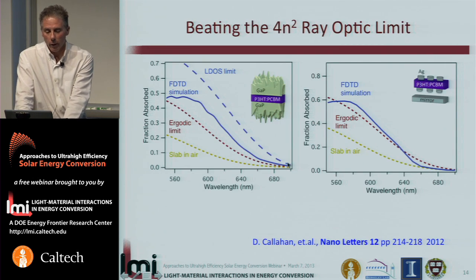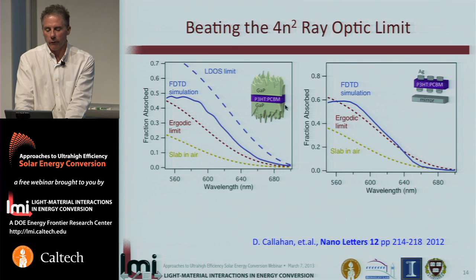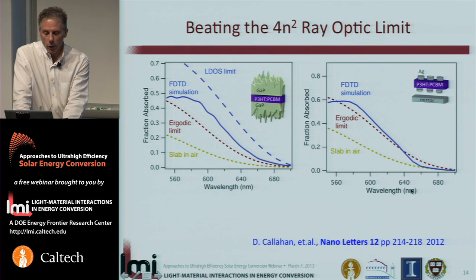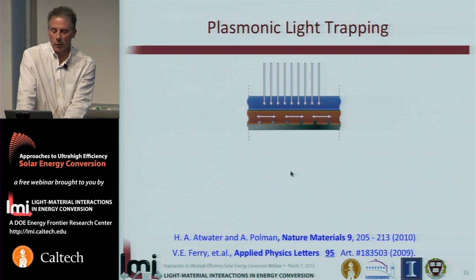And here's a couple of examples of structures, illustrated with an organic polythiophene semiconductor absorber layer, in which high dielectric constant cladding layers can allow one to exceed the ray optic light trapping limit. And here an array of optical antennas clad around the absorber layer accomplishes the same thing. In fact, we can also think about using metallic structures, and there's been a great deal of thinking and progress and experimentation on so-called plasmonic light trapping, in which metal dielectric structures that support localized and propagating plasmons can act as mode converters, converting incident sunlight into waveguide modes in a thin film solar cell, whose thickness might be in the optically thin regime without such a structure.